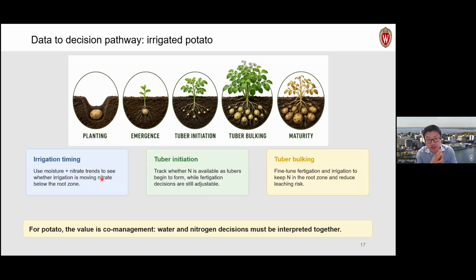However, when we apply this to irrigated crop production, the information could be more complicated. First, we need to optimize irrigation and nitrogen fertilization, or fertigation, at the same time. Sometimes we want to make sure the moisture and nitrate are both optimal, but also be aware that when the moisture is too high, it also creates a risk for nitrogen leaching. So this creates more information for us to make a decision. It also gives us more information about the key points where people should start thinking about when to target our nitrogen application, so we do not over-fertilize our plants, which can create a problem, especially in coarse texture soils.